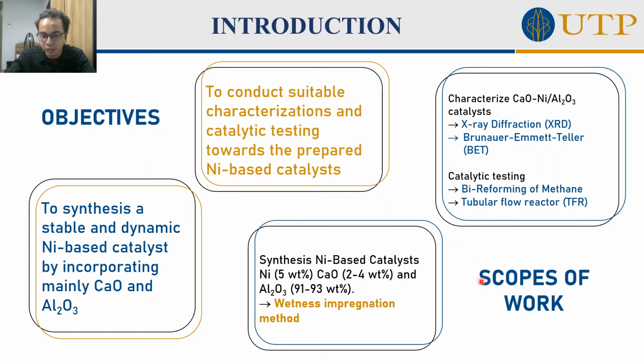For the scope of work, I've synthesized nickel-based catalyst with a constant weight percent of nickel, which is 5 weight percent, and distinct weight percent of calcium oxide, which is 2 and 4 weight percent, by using the wetness impregnation method. For the characterization, I've employed two techniques to examine the properties of the catalyst, which are XRD, X-ray diffraction, and also BET. To check the stability of the catalyst towards the purpose of this project, bioreforming of methane, I've employed the catalyst in the reaction using a tubular flow reactor.